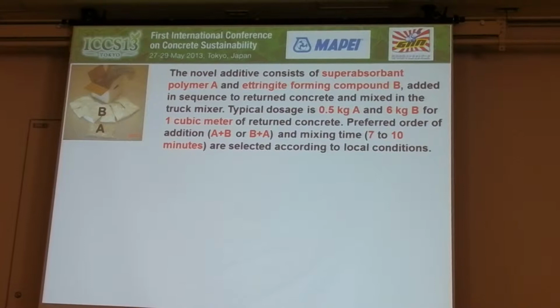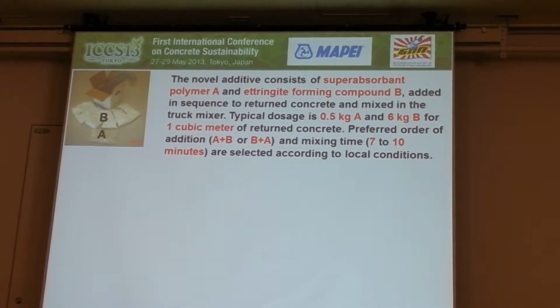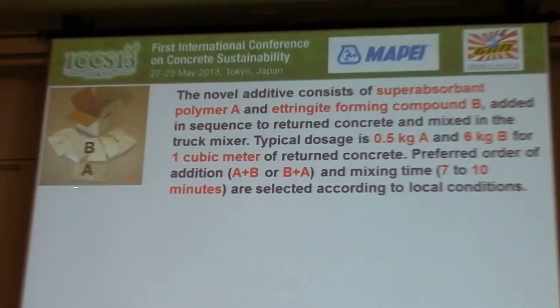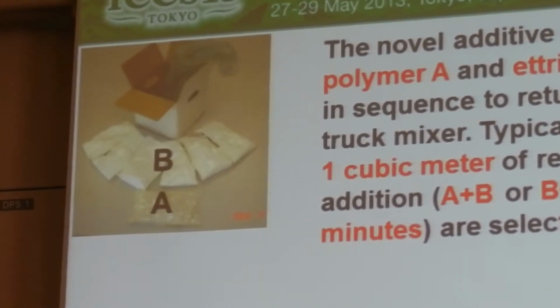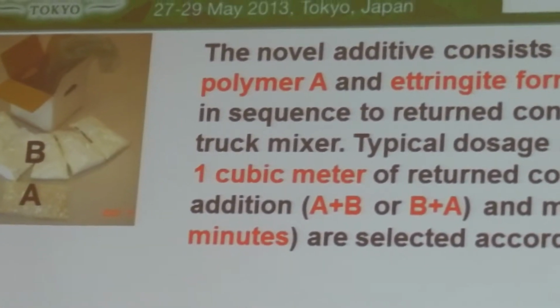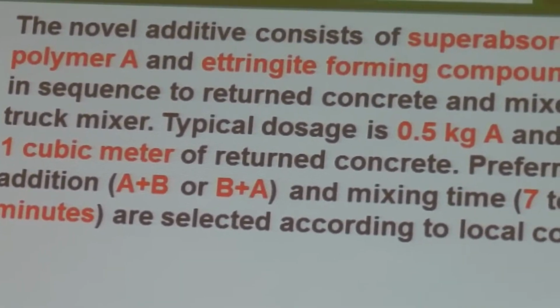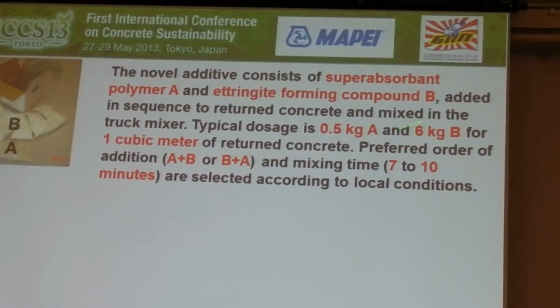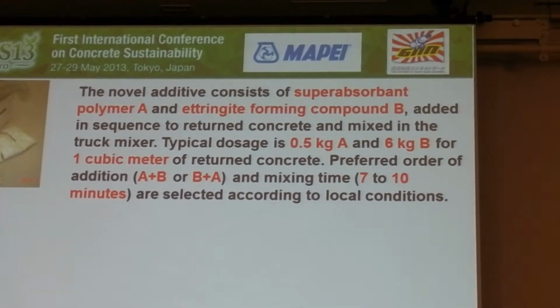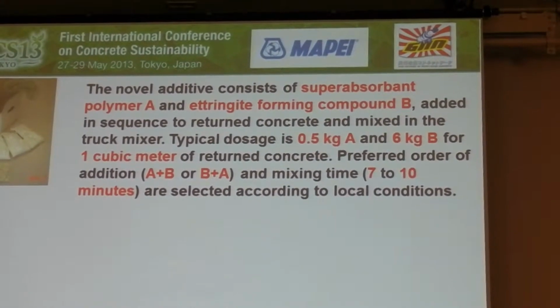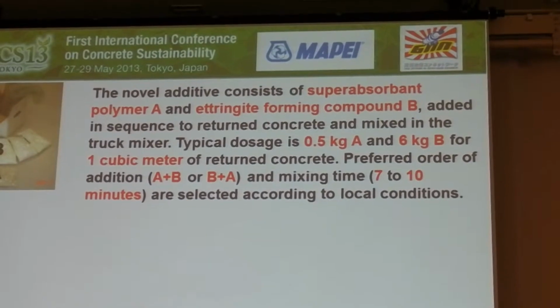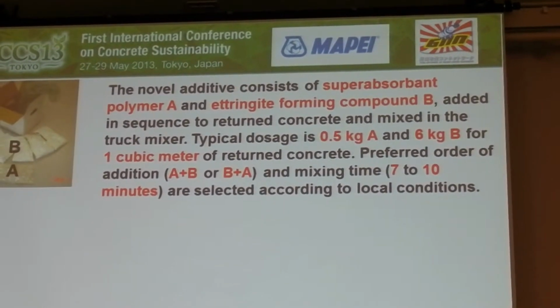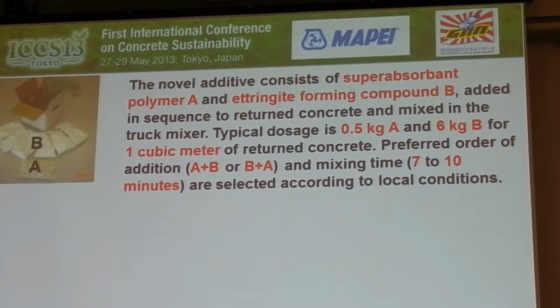The novel additive consists of a superabsorbent polymer, part A, which is in a water-soluble bag, and a component B, which is an ettringite forming compound, that are added in sequence to returnable concrete directly in the truck mixer and mixed together. The typical dosage is 0.5 kilogram of part A and 6 kilogram of part B per 1 cubic meter of returnable concrete to be treated. The preferred order of addition may be first part A and then part B, or vice versa, first part B and then part A, according to the local condition. This means the type of cement, the water to cement ratio, and other variables.